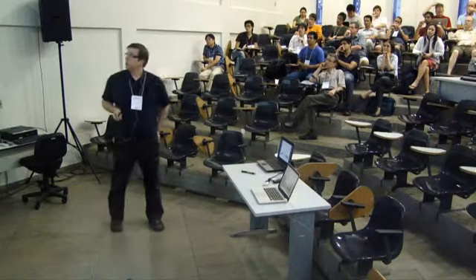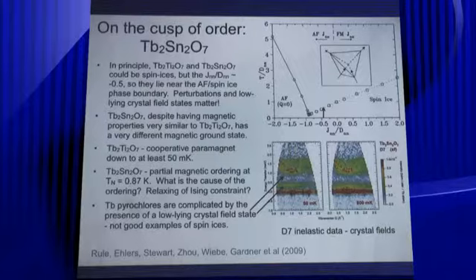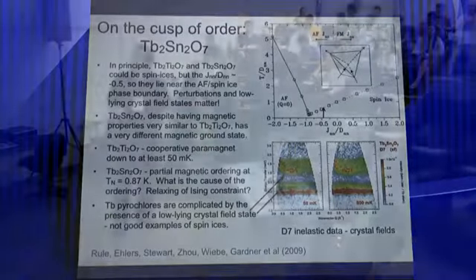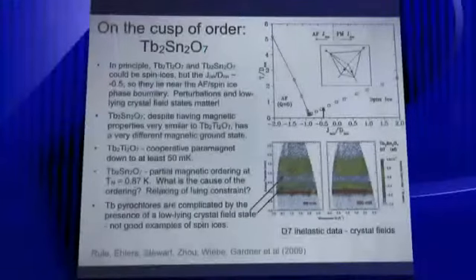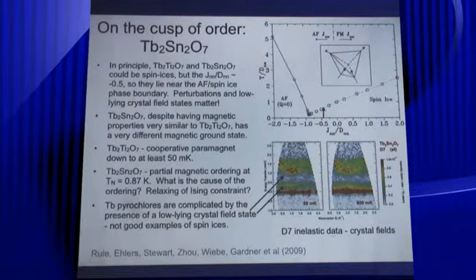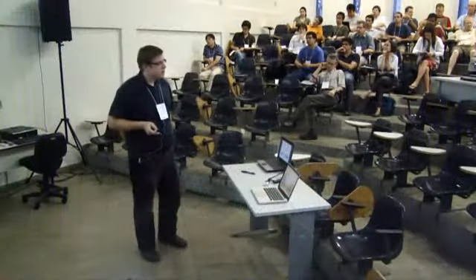Okay, so I'm just mentioning this as a cautionary tale, right? If you have other terms in the Hamiltonian, like crystal field effects, you basically can't use this phase diagram anymore. So for example, if you look at terbium titanate, terbium stannate, you can look at J over D, you get roughly -0.5, so you might think, oh, if I make this compound, it's going to be a spin ice. It's not, right? It's not because we're only including this exchange term and this dipolar term in the Hamiltonian. As Michel Gingras pointed out, you can think about different axes that can come on here for different other effects, such as crystal fields. And crystal fields are extremely important towards understanding the terbium titanate and terbium stannate, right?